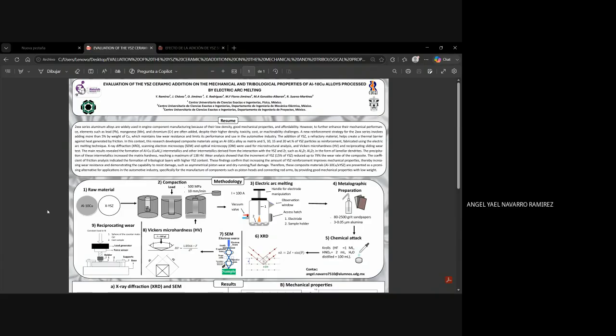the research developed composite materials, using an aluminum 10 copper alloy as matrix and 5, 10, 15 and 20% of YSZ particle reinforcement, fabricating composites with a total weight of 2.5 grams. When I obtained all the compositions, they passed to compaction. In the compaction, the press used a load of 500 megapascals to obtain the compacts.